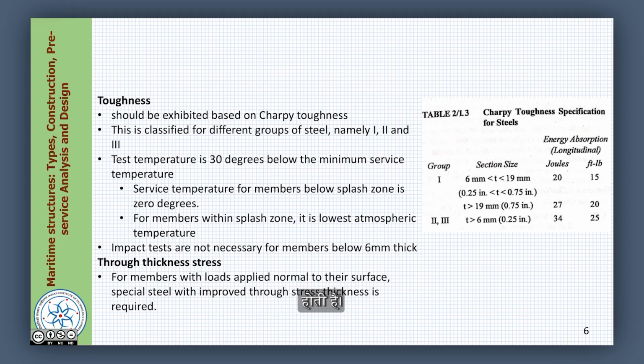When you want to group them based on Charpy's toughness index, then Charpy's test needs to be conducted. That test is conducted at a temperature 30 degrees below the minimum service temperature, whereas the service temperature for members below the splash zone is 0 degrees. You know what a splash zone is? Let me try to draw a figure. We already said that, but still we reiterate it.